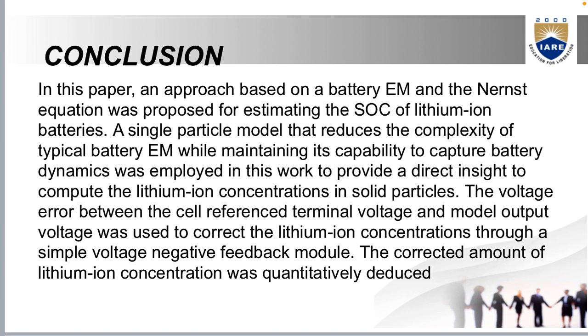Conclusion. In this paper, an approach based on a battery EM, the Nernst equation, was proposed for estimating the SOC of lithium ion batteries. A single particle model that reduces the complexity of the typical battery EM while maintaining the capability to capture the battery dynamics was employed in the work to provide a direct insight to compute the lithium ion concentrations in the solid particles. The voltage errors can be used to correct the lithium ion concentrations through a simple voltage negative feedback module. The corrected amount of the lithium ion concentration was